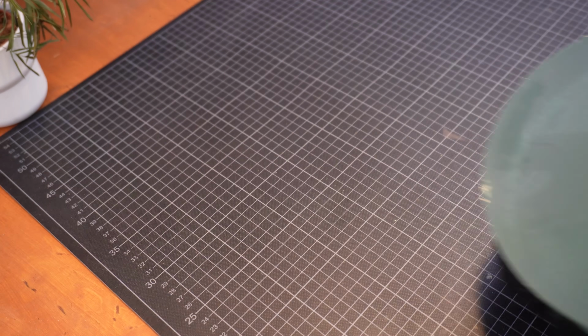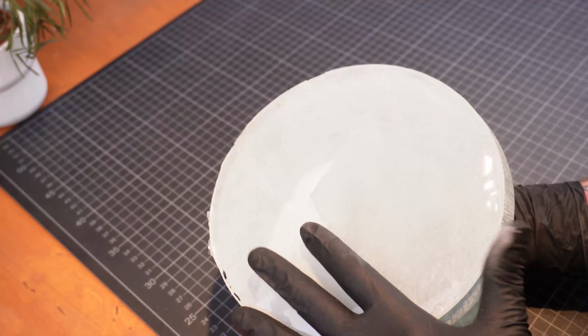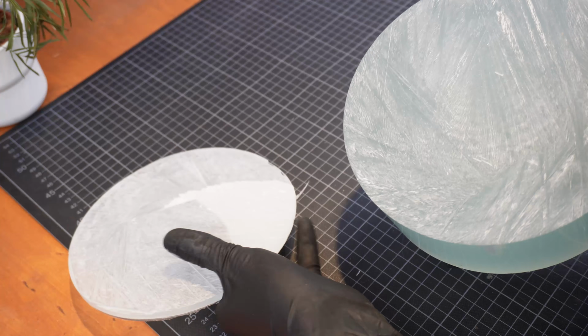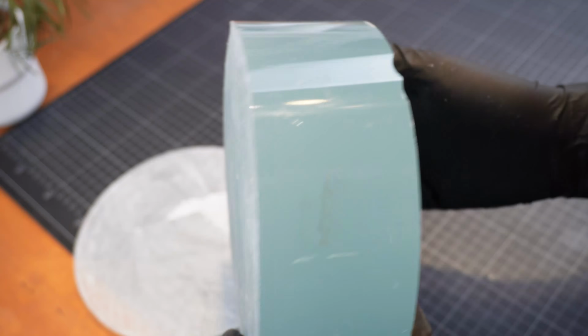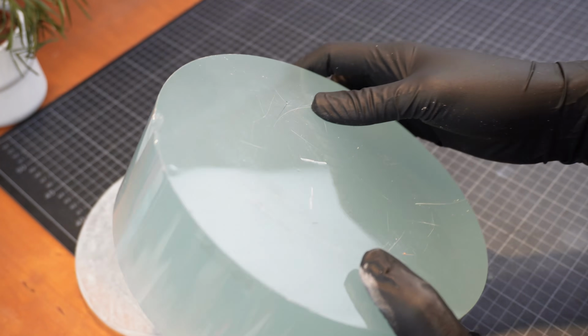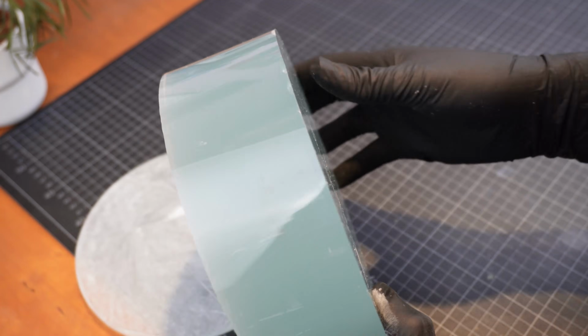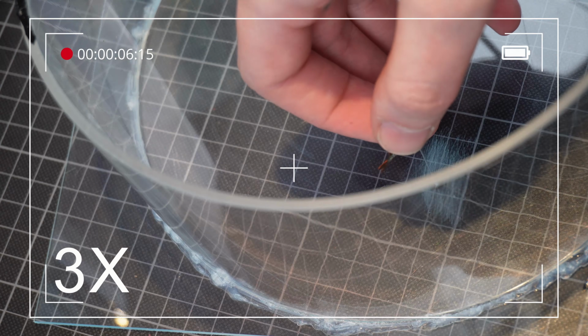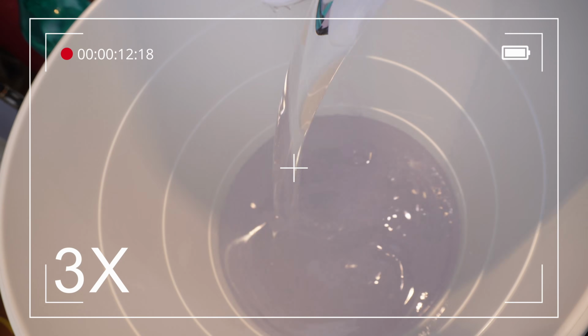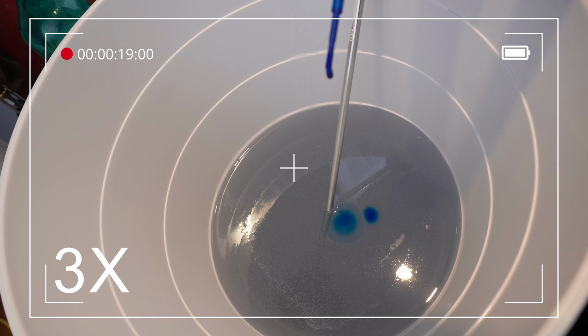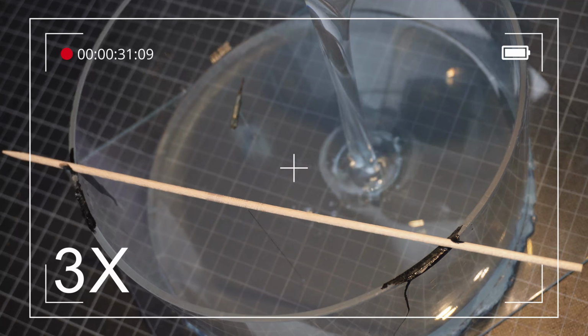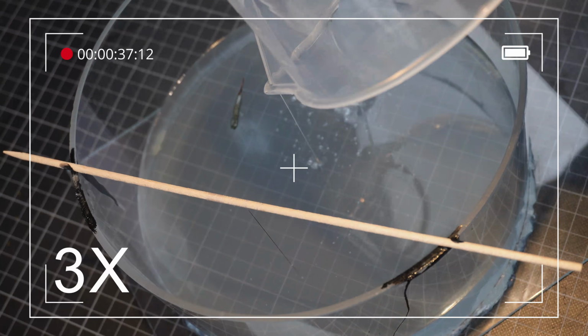For some reason, that day when I did this pour, it was especially hot, and after about 4 hours the resin started cooking off and left all those ugly marks that you were able to see on the lower side of the block. So for my third try, I went back to this slower resin, and as you can see, this didn't look that bad at all. I was able to remove the mold without any issues since I finally knew how to do it.